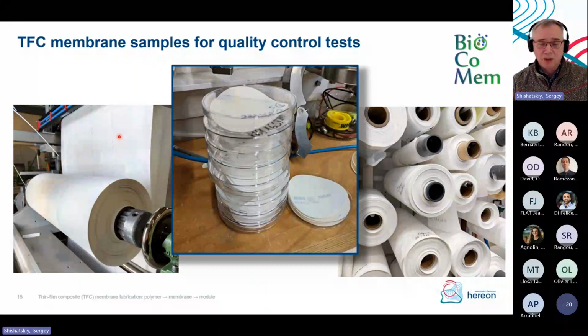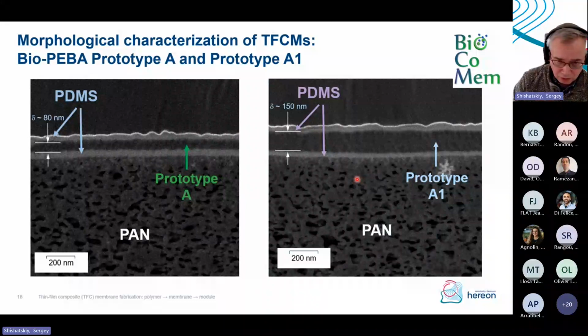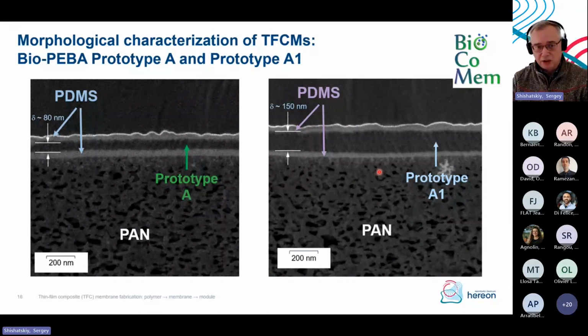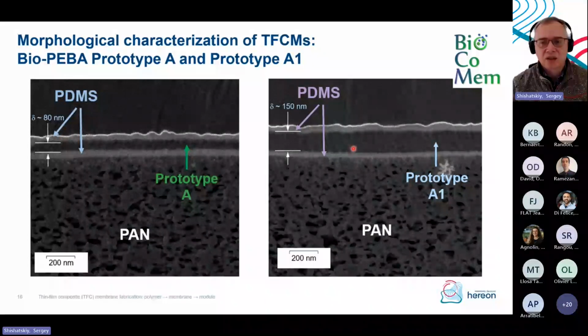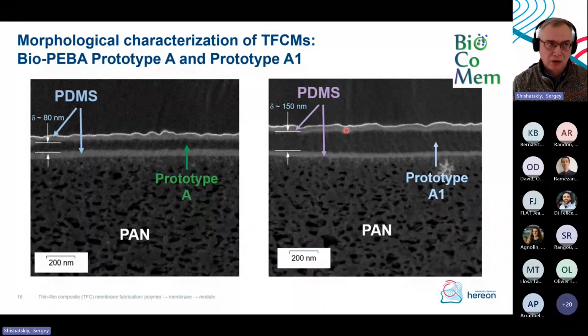Along the membrane production process, you can take stamps. You can just cut pieces of the membrane and have a stack of them. Then you send this roll of membrane to the storage, and then you start to investigate the internal morphology of the membrane and gas transport properties. So you can see here examples of two membranes which were developed within the Biocomem project, of prototype A and prototype A1 polymers. And you can see that we achieved in the first case a thickness of roughly 80 nanometers. And in the next case, we decided to increase the thickness to 150 nanometers due to some interesting effects which we observed during production of the first prototype A membrane.